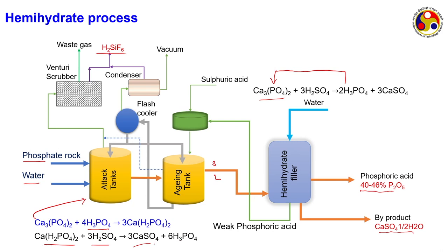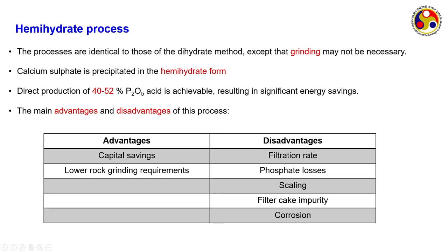The weak solution of phosphoric acid from the aging tank reacts with the ore to form calcium hydrogenphosphate, which then reacts with sulphuric acid to form CaSO4 — written without the half H2O because that crystal form is determined in the hemihydrate filter. The gypsum in this case is the calcium sulphate, and you have phosphoric acid. One key difference from dihydrate is that grinding may not be necessary, saving capital cost. This method is suitable for any type of ore.